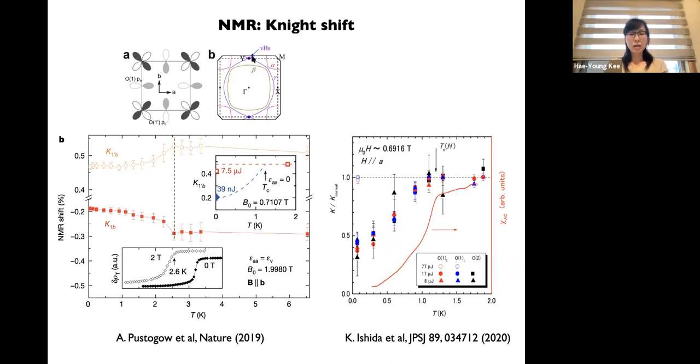You can see they put some uniaxial strain, and once you put the uniaxial strain, TC grows a bit. Epsilon aa is equal to epsilon b, meaning that the strain is such that the system hits the Van Hove singularity at this point, and that's where this measurement was done.